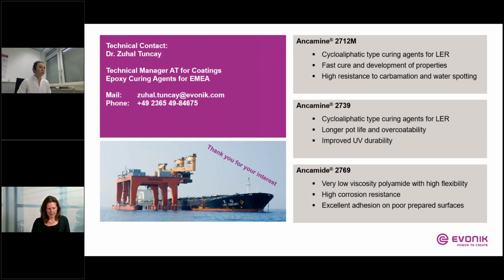One data point which I showed very briefly during the presentation was the pull-off test for 2739 in anti-corrosive primer, where we got a very good adhesion. The results here were around 5 megapascal. But I think there is more behind that question, and it's more about what kind of adhesion we can achieve with that curing agent. In all cases, we do observe very good adhesion to different metallic substrates. But please contact me again and we can discuss it offline. Yeah, I think that's a good suggestion.